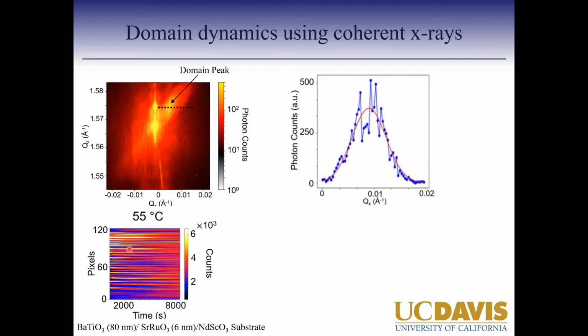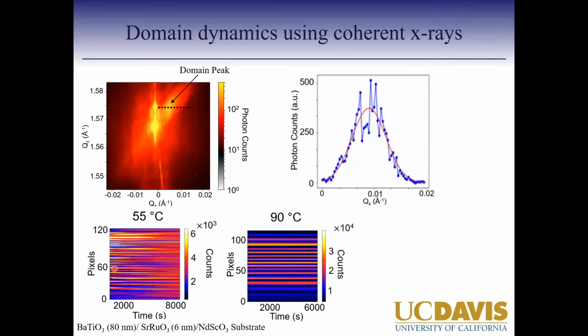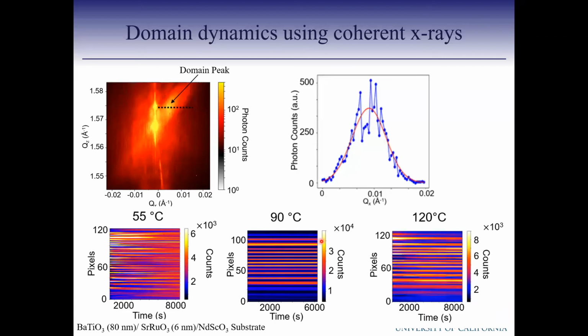So at 55 degrees Celsius, this is the line cut across here, and tracking that as a function of time, I can see that the speckles disappear and appear as the time moves on. At 90 degrees Celsius, the speckles are exactly stable. There is nothing happening. The bright speckle stays bright and the dark stays dark. And then again, at 120 degrees Celsius, you start to see these fluctuations. So this is a very nice way to use reciprocal space to look at how my material is changing. In this case, you have no change. So the sample is static. There is no change in domain structure whatsoever. But around 55C and 120C, the sample is changing. So let's look at what's going on there.